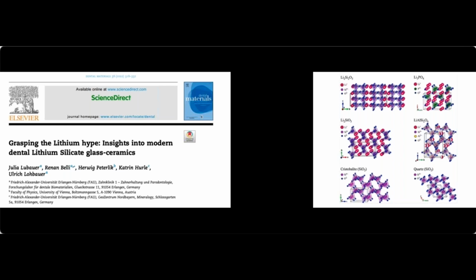And I'm going to show you some micrographs at the end. But basically what happens when you put a lithium silicate in the oven, this needle-shaped crystal starts growing, and they crisscross each other like this, and it creates like a backbone skeleton that keeps cracks from propagating as much, making this material quote-unquote stronger for you. So that was the magic of lithium silicates, to change the way the crystal structure was, even though it's a glass ceramic, to make it more resilient, more tough.